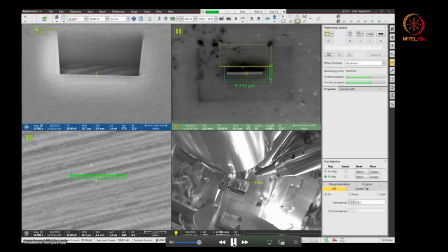This high energy gallium sometimes damages the sample too much, but normally nickel based super alloy and titanium alloy are fine. Now it's almost trenched. I think 20 seconds are left. Yeah, around 20 seconds. Almost it trenched the top part.